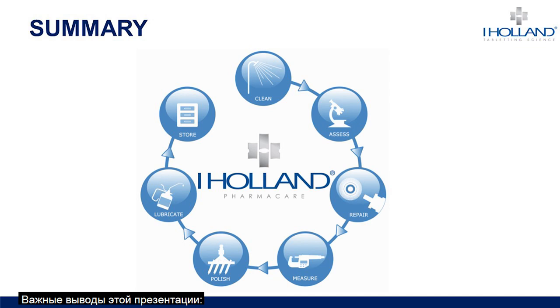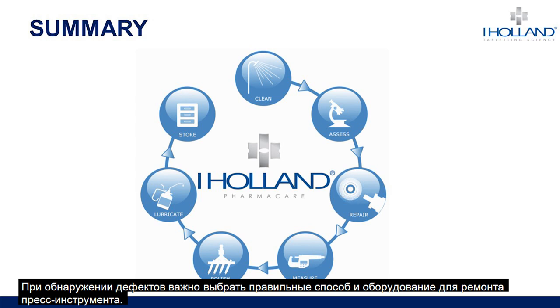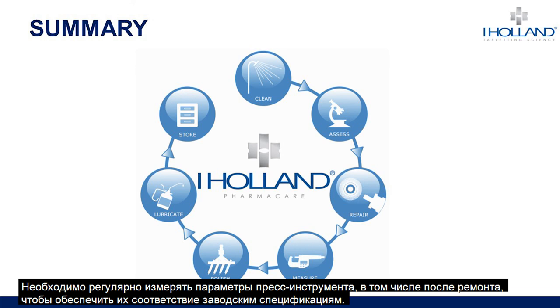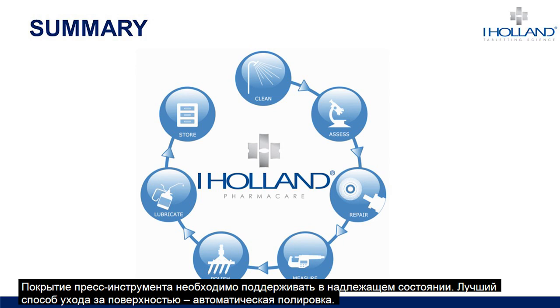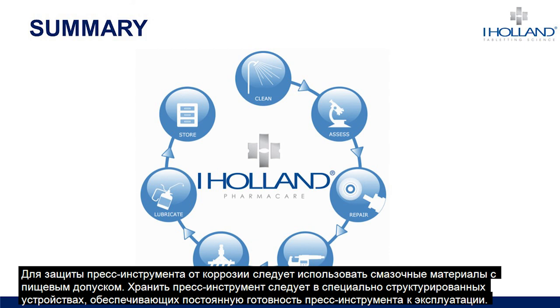The important things to take away from this presentation are: cleaning is important to ensure that tooling is free from dirt or contamination; once cleaned, tooling can be properly assessed for signs of damage; if damage has been found, use the correct procedures and equipment to repair it; tooling should be measured routinely and after repair to ensure it is still within specification; the surface finish needs to be maintained, and the best way to do this is automated polishing; food-grade lubricant should be applied to protect tooling from corrosion; and finally, tooling should be stored in a secure, organised manner so it is ready for use. As discussed, 85% of tooling damage occurs due to poor handling — it is therefore important to follow a planned professional maintenance procedure with suitable equipment to protect and maximise the usable life of the tool.